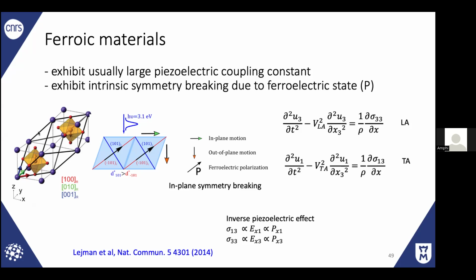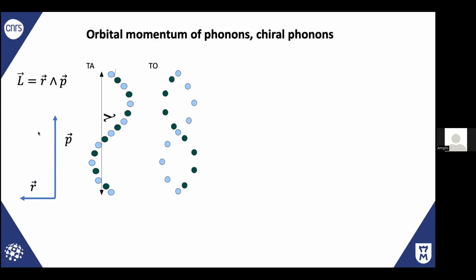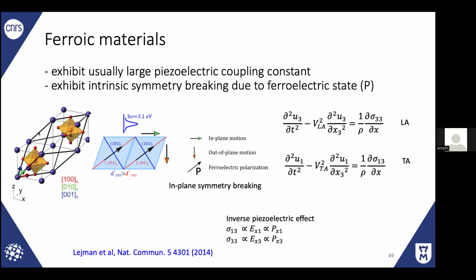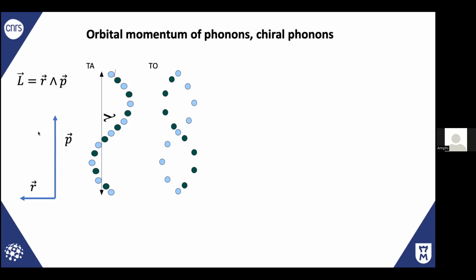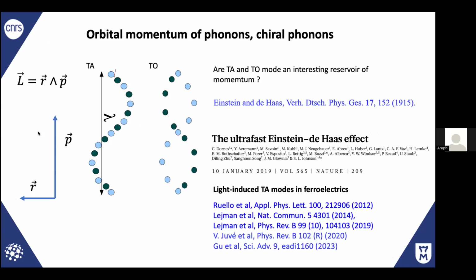And in that case, we discussed a couple of years ago the piezoelectric effect that can induce longitudinal and shear motion. To have shear motion, you have to break the in-plane symmetry, and this is exactly what you can play with a ferroelectric material. And the transverse acoustic phonons are also very interesting because these transverse, either acoustic or optical, hold a momentum. This is important in the community because this momentum is also related to chiral phonons, which can be used maybe in the situation of the conservation of momentum in the case of demagnetization, for example. So it is important to understand how we can induce transverse acoustic phonons with light.